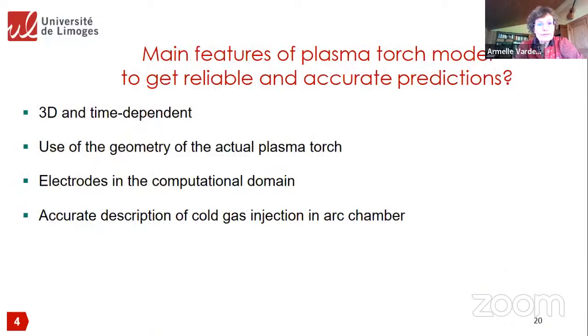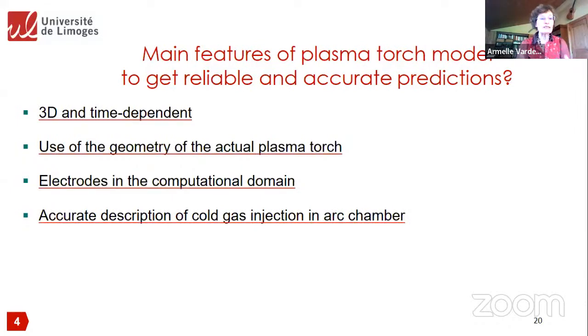Okay. Now, which are the main features of a plasma torch model to get reliable and accurate predictions? I am giving a list. This list results from our own work, but also from the literature and from the many publications by the labs working in this field, not only thermal spray, but also welding and cutting with plasma torches. So one of the important features is to have a 3D and time-dependent model. We have to use the actual geometry of the torch and not a simplified geometry. We have to have the electrode in the calculation domain, and we need an accurate description of the cold gas injection in the arc chamber. If the gas is injected with a swirling injection, you need to have the swirling injection as input data in your model.